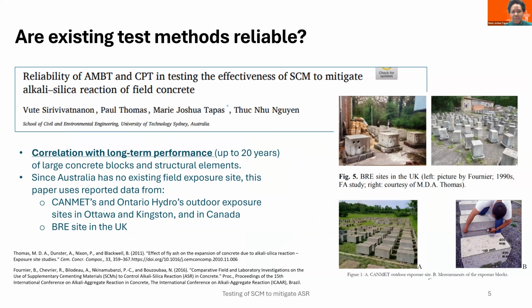Again, I think Professor Marjorie has already mentioned her presentation. The only way, the best way, is really to do a long-term performance test, okay, field data. When we're using accelerated test methods, say you're having a 21-day test result, and you're guaranteeing that your structure will not suffer from ASR for the next 50 years, if your design life is 50 years, for example.